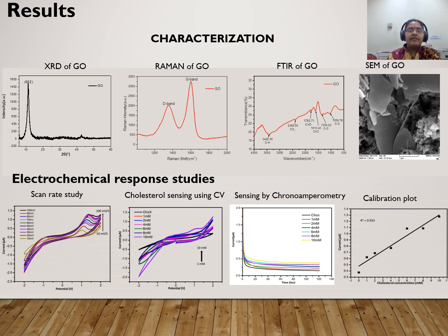In these studies, first we have taken the enzyme electrode and carried out the scan rate study at different scan rates from 10 millivolts per second to 100 millivolts per second. The current increases with the scan rate, which implies that the charge transfer process taking place in the present study is diffusion controlled. And we have done the cholesterol sensing using different concentrations of cholesterol solution, like 1 millimole, 2 millimole, 4 millimole, up to 10 millimole, and the change in the current is clearly visible in the cyclic voltammetry studies.